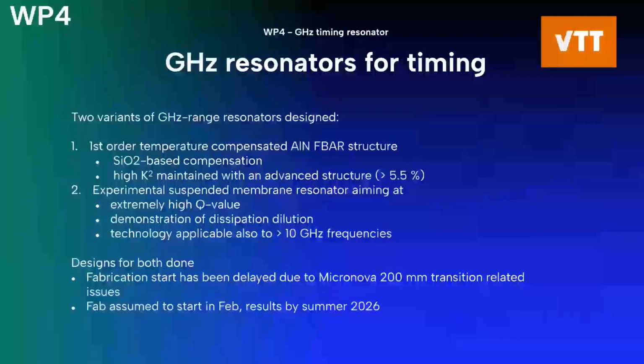Then going to work package 4, gigahertz resonators for timing. So there's a demand for resonators with the native or the fundamental frequency at the gigahertz range out there, and we have designed 2 different variants to this need. One is a first order temperature compensated FBAR using good old silicon dioxide based compensation, but we have come up with a design that maintains very high coupling coefficient while being first order temperature compensated. So we have a K-squared of 5.5% expected from these devices.